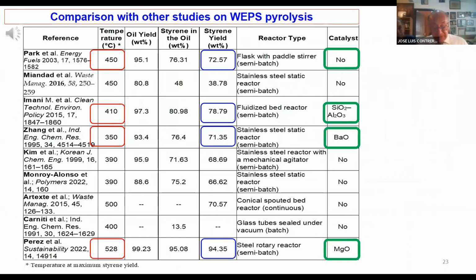In comparison with other studies on the pyrolysis of waste, we observed that the majority of the studies with styrene yields greater than 71% used catalyst. Also, the reaction temperatures varied from 350 Celsius with Zhang to 528 Celsius with Perez. As might be expected, styrene performance is more favorable at high temperatures. The studies by Zhang at 350 Celsius and Imani at 410 Celsius could be interesting, with yields of 70% and 78% respectively, due to the low temperatures they used.